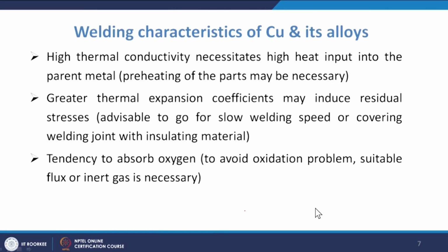Welding characteristics of copper and its alloys: high thermal conductivity necessitates high heat input into the parent metal. Preheating of the parts may be necessary. Greater thermal expansion coefficient may induce residual stresses, so it is advisable to go for a slow welding speed or cover the weld joint with insulating material. Tendency to absorb oxygen: to avoid oxidation problems, suitable flux or inert gas is necessary.